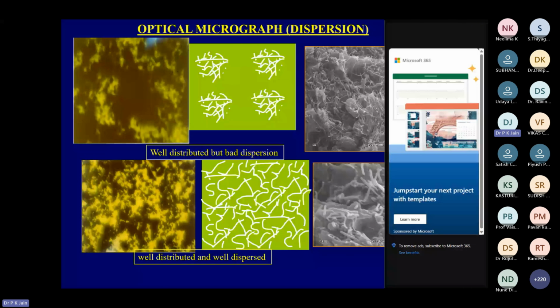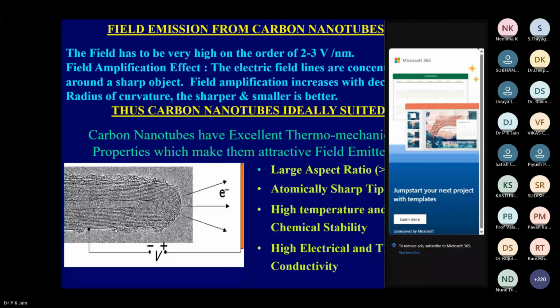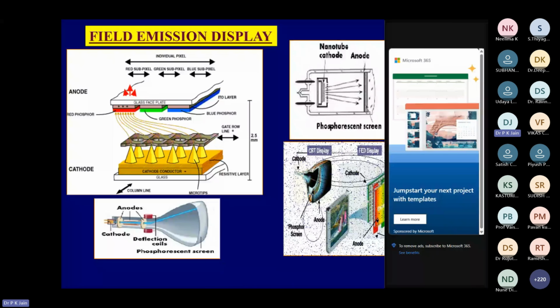This is, as I told you, field emission. Carbon nanotubes are one of the best field emitters because their diameter is in nanometers, so they can emit. There's a reason they have a large aspect ratio: the diameter is too small and the length is in microns while the diameter is in nanometers, so the aspect ratio is more than 1000. The tip is atomically sharp, which you cannot make with any material unless it is naturally made. And there's a reason: earlier, the television was bulky at the back, as CRT, cathode ray tube, was used. Now we use a TV which is like a laptop, very thin, because the emitters are different.